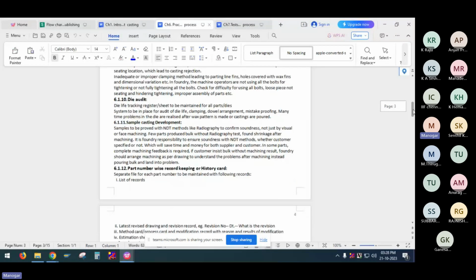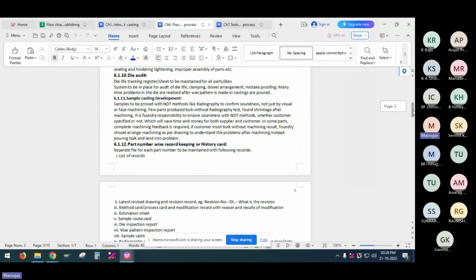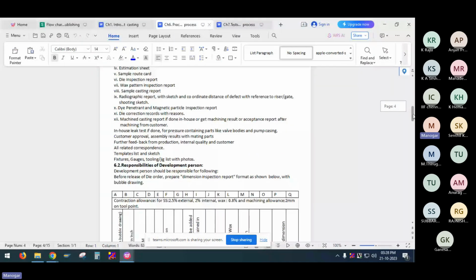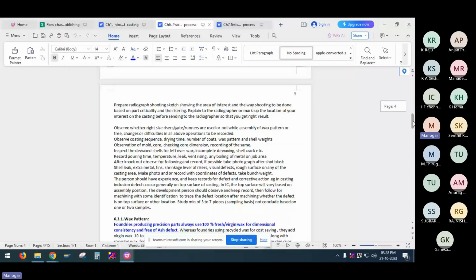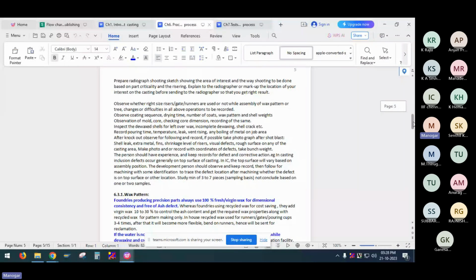In sample development, we know all the other dimension inspection, visual, everything. What I want to emphasize here, especially in sample development, is that when castings are subject to NDT tests like radiography, those castings should be properly inspected before sending to radiography. Note down where your gate position is, whether it is on the top side or bottom side, and if necessary mark it or take a photograph and give it to the radiographer. Also ensure there is no visual defect or visual marks on the casting, because even minor line marks or small fins will be seen in the radiographic film. Then it will confuse whether it is a defect or it is due to the die itself. So it is better to inspect the casting properly before it goes for RT. That is a very important thing.